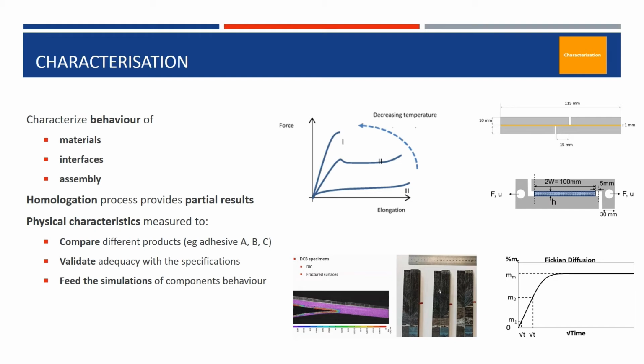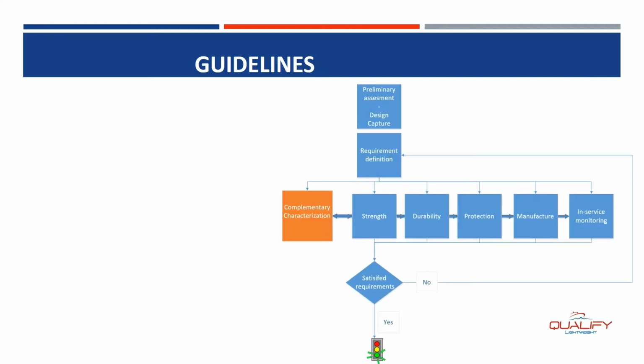Finally, there's a part on characterization, the idea being to characterize the behavior of the material, of the interface, of the assembly. And it will be something on top of the homologation, which will give the partial results. And the idea is to measure the physical characteristics so as either to compare different products, adhesive A, B, C, or surface preparation A, B, C, validate the adequacy of the design of the material to the specification, for example the glass transition temperature, and feed the simulation, like the Young modulus, the shear modulus, the strength, or the diffusion coefficient for the durability.